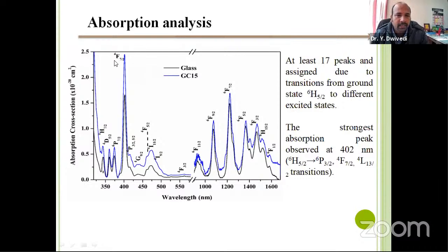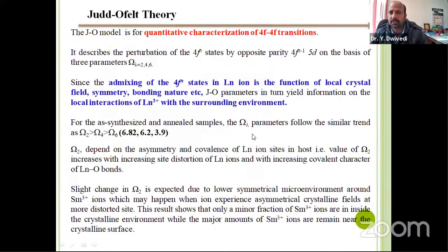But you see, in case of glass ceramics, this absorption cross section is a little bit higher than the glassy phase, this black line. But this increment is not uniform. In some cases it is too much, and in some cases it is a very small increment. This is happening because of transition to transition variation. If the nature of the transition is hypersensitive, you see good enhancement; otherwise there is very less enhancement.